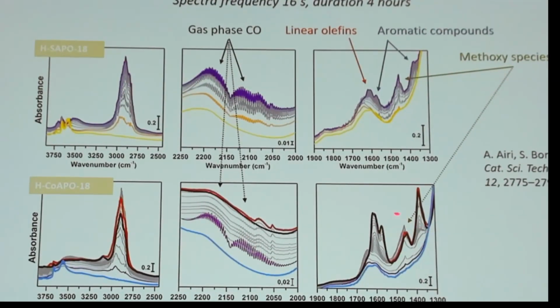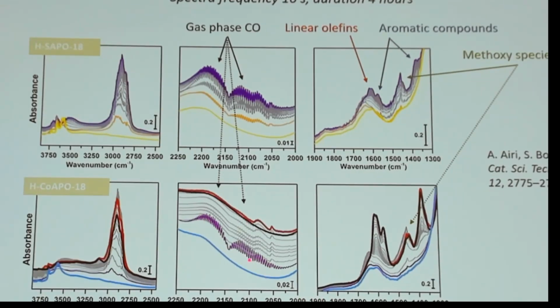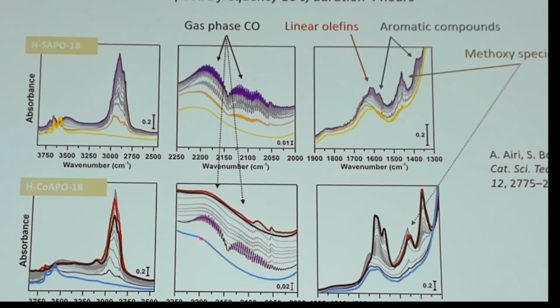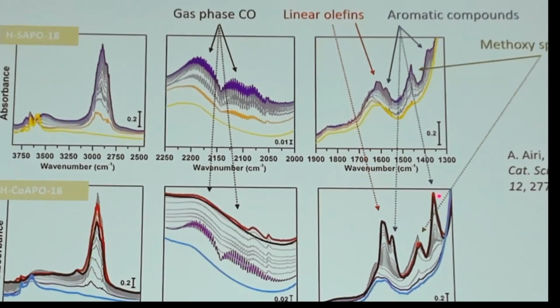If we now go to the cobalt AlPO-18 structure, then we see that it's the same thing. The methoxy species are formed, and we also see that CO is formed very rapidly in the first 16 seconds. But then something interesting happens, because this CO signal is declining very rapidly. So CO seems to be consumed in this case. And we also see now that we do form linear olefins, but we also see much more abundant formation of aromatic species in this cobalt AlPO-18.